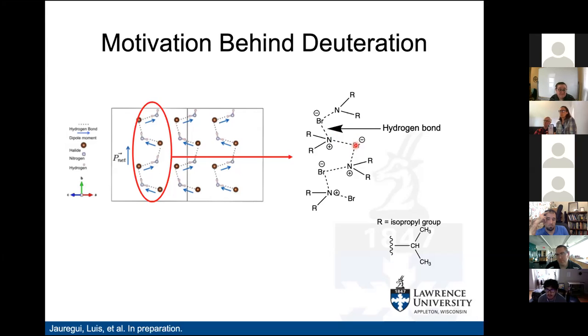In order to probe into the hydrogen bond, deuteration studies are used to shed light into the dynamics of the phase transition. Deuteration has helped understand the phase transition in other ferroelectric materials, such as potassium dihydrogen phosphate. When potassium dihydrogen phosphate was deuterated, the phase transition temperature jumped up about 100 degrees Celsius, so there was evidence that deuteration did affect the phase transition temperature in some way. We are hopeful that deuteration will help us understand the phase transition of DIPA bromide.